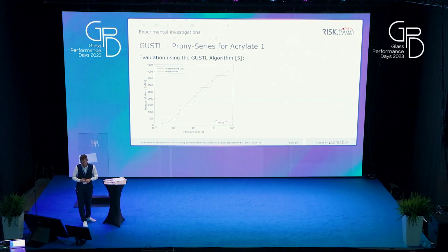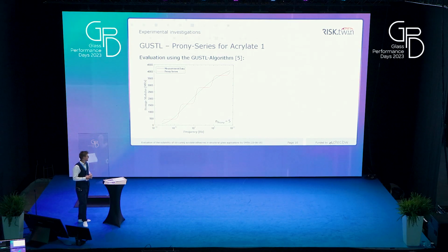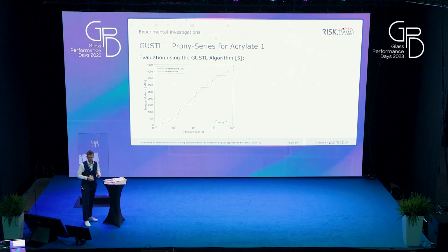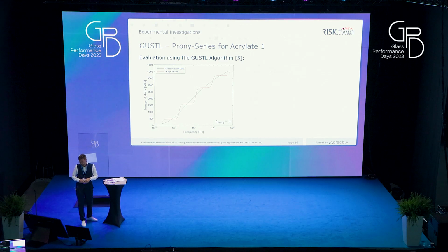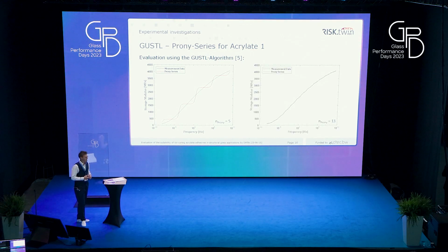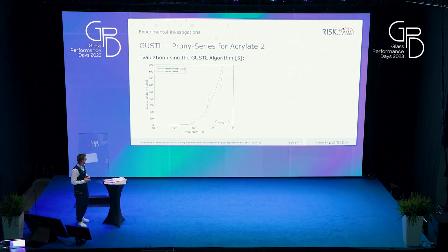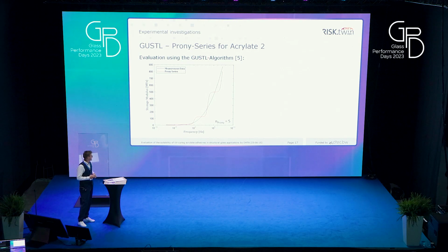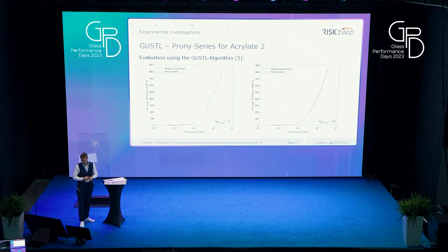So if we tried to fit the curve with 5 elements, since the single elements have only a specific area of influence, the curve is not fitted very well. But if you use 13 elements for Acrylate 1, the depiction is quite good. Same thing for the second adhesive. Again, 5 elements, not sufficient, but here with 12 elements, the depiction is again very good.